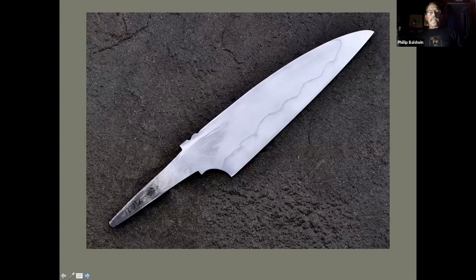There's the hamon. I've got some nice brush strokes and sand thing going on at the very base where it was a little bit cooler. This particular sort of hamon, where the transition from hard to soft steel is very abrupt, is characteristic of very high carbon steels, and that's what my blades tend to be. If I made a blade like this out of drill rod, which is about the same carbon content, it would look very similar. We would not get that figure towards the base of the blade where the transition to the tang is. If it was lower carbon, we would get a more interesting figure in it. Next slide, please.